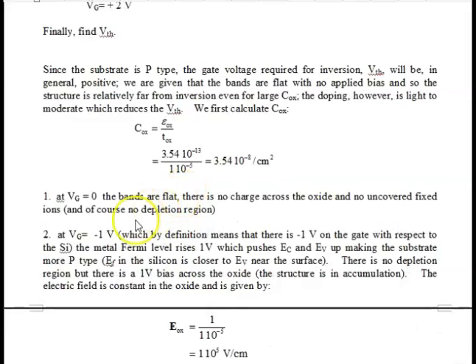Okay, so of course, in the first case, where we have equilibrium, flat band, there is no charge any place, and there are no uncovered fixed ions, and of course there is no depletion region. At -1 volt, this is the case we just looked at in our energy band diagrams. This would be in accumulation. Now, it doesn't matter what the oxide thickness is. Put -1 volt for work function difference equal to 0, I'm in accumulation. I may not be as great in accumulation, or maybe less, depending on the work function difference, but certainly it's going to be accumulation.